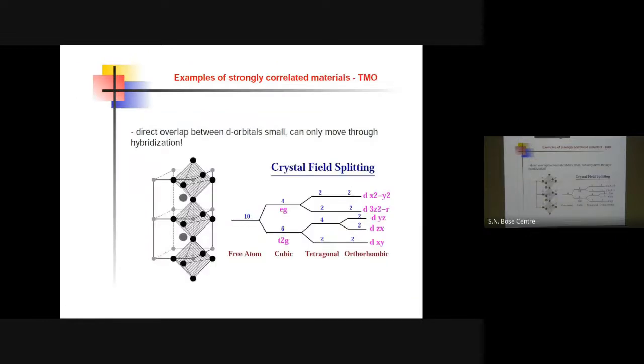So the other example, and probably all my examples will be drawn from this family, is that of the transition metal oxide. I just said the transition metals are metals. So they still have not gone to the extreme situation of complete localization and giving rise to an insulator. But if I make these transition metals sit far from each other, as in the transition metal oxide, here each transition metal is surrounded by oxygen, because they are not only transition metal but also oxygen. So one d electron cannot even directly see another d electron. It has to pass via this oxygen. That makes the correlation effect of a transition metal, when you make an oxide, even more.